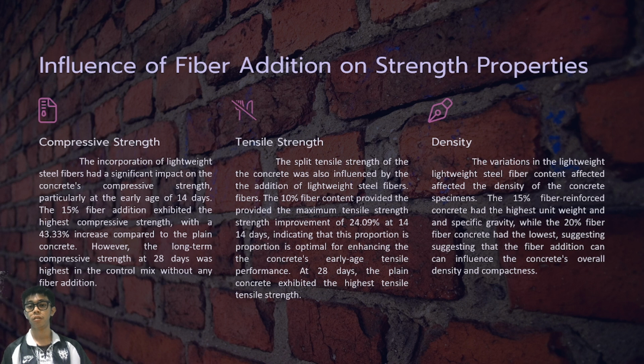Influence of fiber addition on strength properties. First, compressive strength. The incorporation of lightweight steel fiber had a significant impact on the concrete compressive strength, particularly at the early age of 14th day. The 15% fiber addition exhibited the highest compressive strength with a 43.33% increase compared to the plain concrete. However, the long-term compressive strength at 28 days was highest in the control mix without any fiber addition.